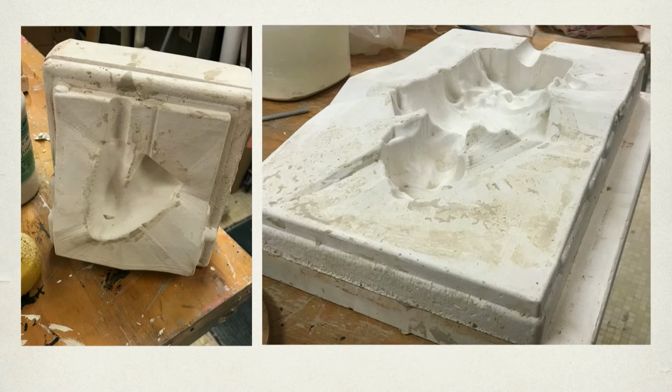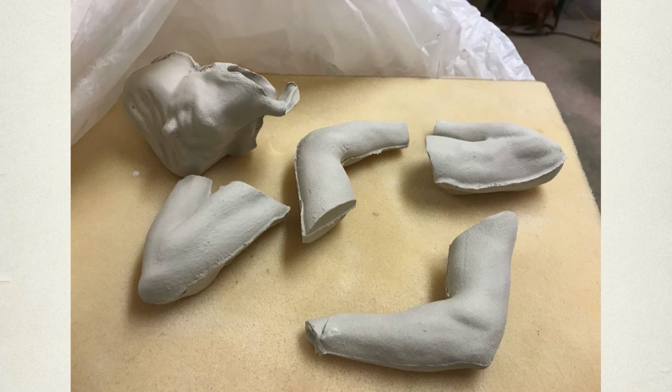So we had the plaster mold, and then final assembly here. The first pull. The mold was, again last minute, pretty wet. Also, we were pushing the limits on a two-part mold. Obviously, there were some vertical side areas that honestly probably would have been better served in a three-parter. But I think my next step would be to start putting airline in the plaster to help eject these parts.